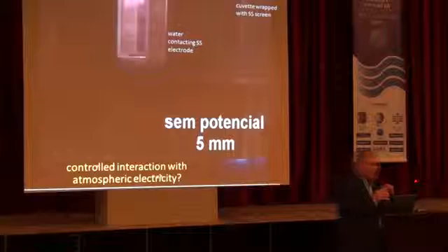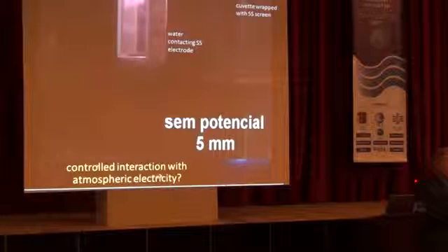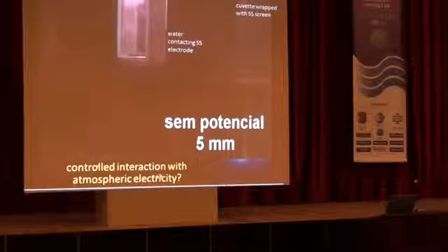If the metals are grounded, depending on the thickness of the oxide layer, you can still see a lot of potential gradients. You cannot go to very high potential, but I say very high is many volts. I think the maximum that we observed is in the range of 1 volt. Because in many cases, take aluminum for instance.